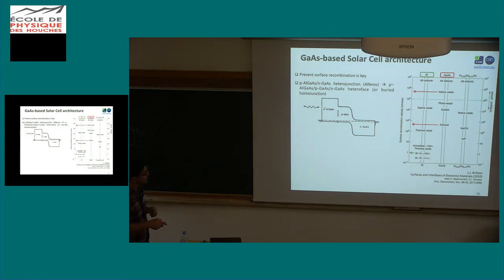And for the silicon, actually, if you use a thermal oxide and use some tricks, some annealing, for example, it can be extremely low. For gallium arsenide, the best we can do, as far as I know, is to use, again, aluminum gallium arsenide. So you have this type 1 heterostructure, so you're preventing the carriers from recombining. You basically prevent having a pinning of the quasi-Fermi level in the middle of the gap somewhere that is then assisting the recombination.